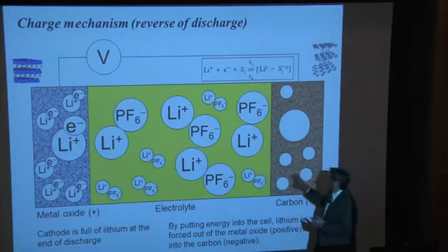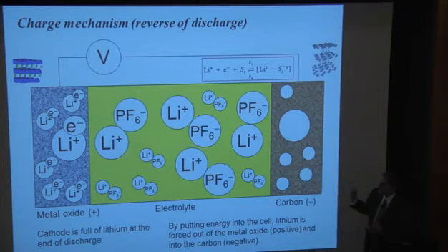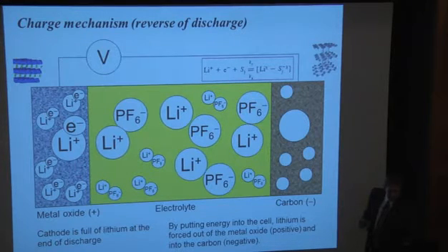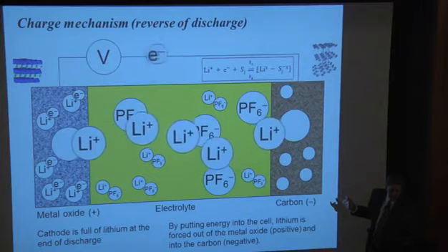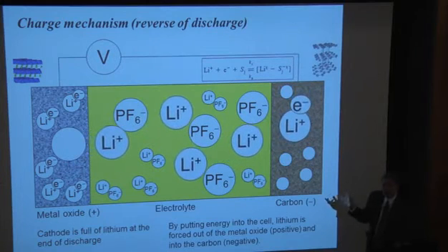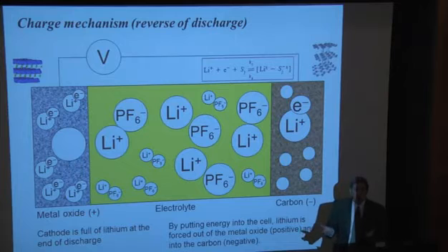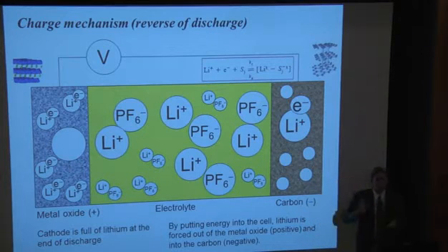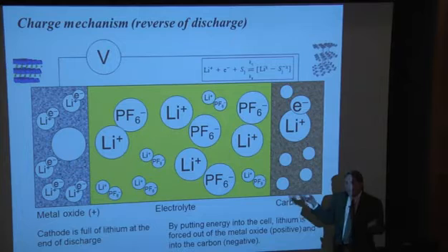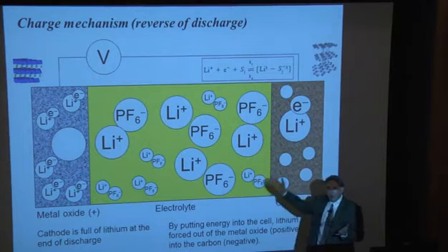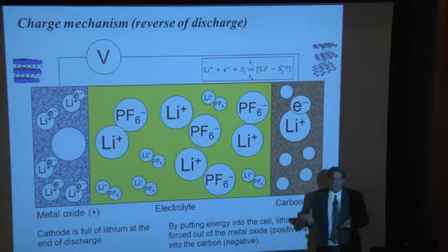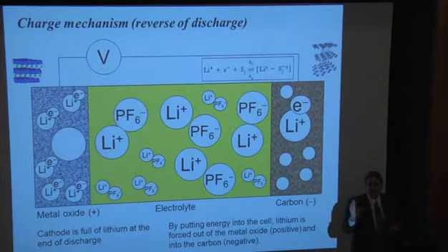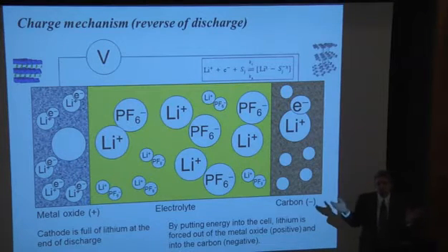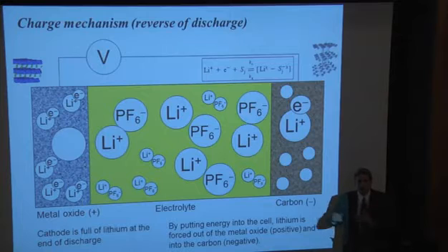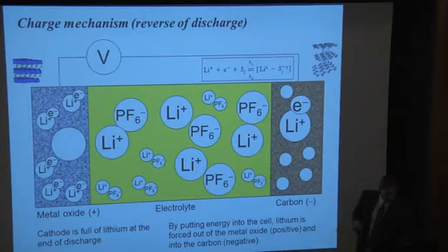Lithium ions then move across to, in this case, the charge reaction to fill the negative electrode, the carbon. And so the reverse reactions happen on discharge. The lithium just comes back to the other side. In fact, when these batteries were first developed, the term rocking chair batteries was used because the lithium rocks back and forth. You might think, well, why would lithium move? Why does it spontaneously discharge from this electrode to the other electrode when it's full? And the answer is it's the chemical potential difference. The chemical potential of lithium is different in the two host materials, and for that reason it spontaneously discharges when you've charged up the carbon electrode.